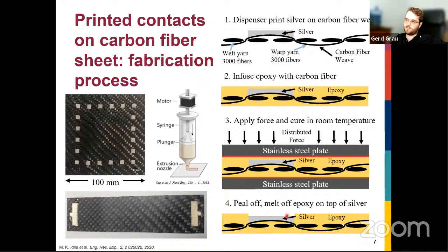And you just have to melt off the epoxy on top of the silver. And now you have a good contact between the silver and the carbon fiber. And then, for example, you can print more silver or other materials to create a circuit, and your carbon fiber is part of this circuit. And so this here would be then the final composite, and you can see these silver electrodes here.